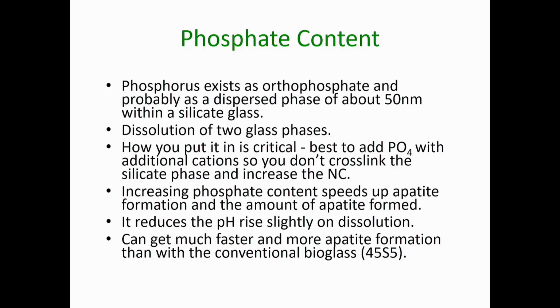As you increase the phosphate content of the bioactive glass, it speeds up the formation of the apatite as well as increasing the amount of apatite formed. It does reduce the pH rise slightly, and by increasing the phosphate content of the glass, you can get much faster and more apatite formed than with the original bioglass, which is known as 45S5, developed by Larry Hench.